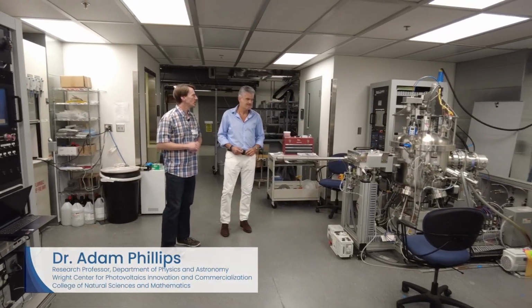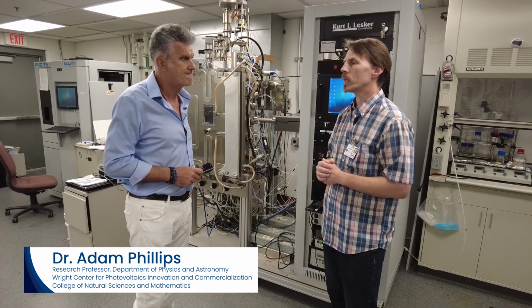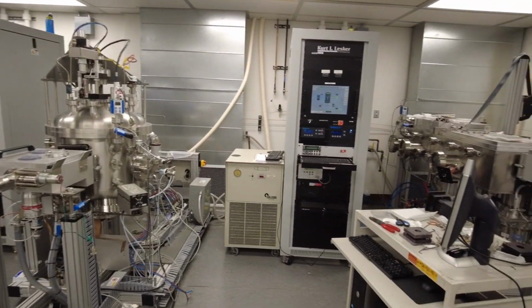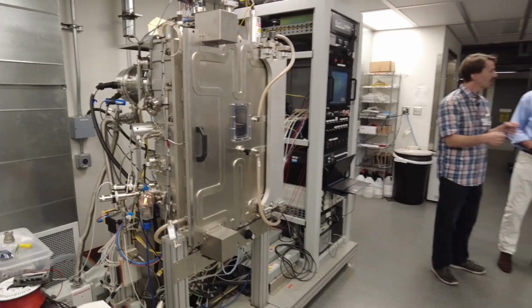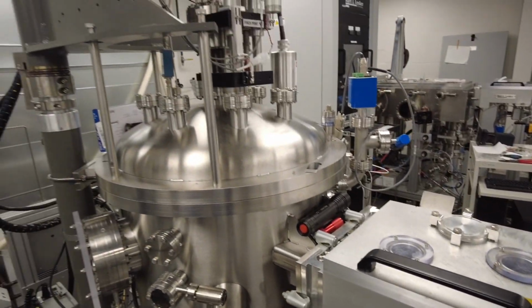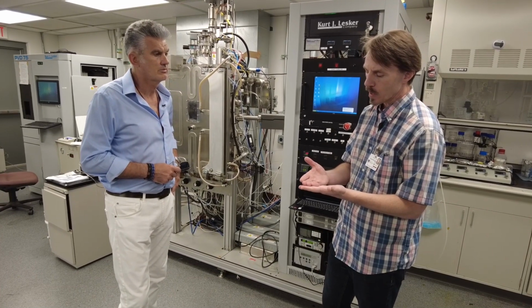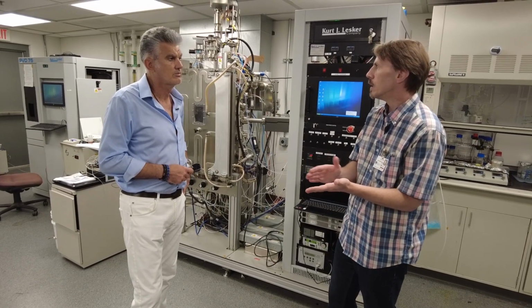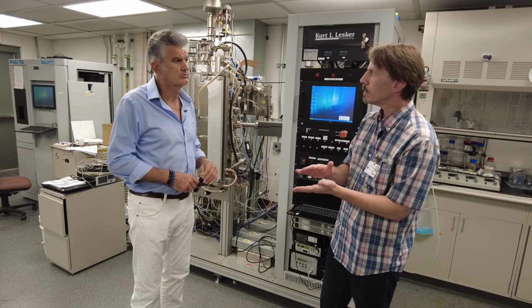This was our original CdTe room. Let's say we're making a CdTe device. We start with a piece of glass from whatever partners we have. It's a piece of glass. It's transparent, but it's not conductive. So we start by depositing a transparent conducting oxide. Then we put down, in cadmium telluride, an electron transport layer or an emitter in the CdTe field. On top of that, we put the absorber.